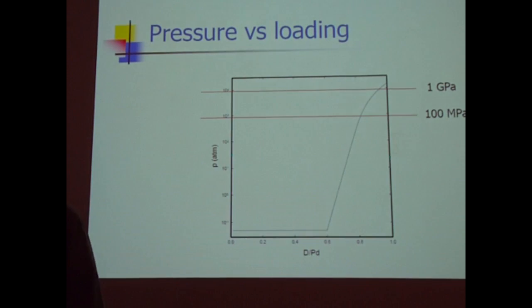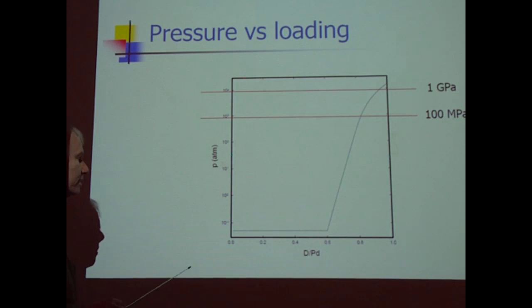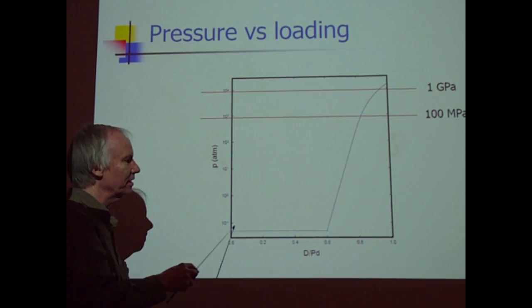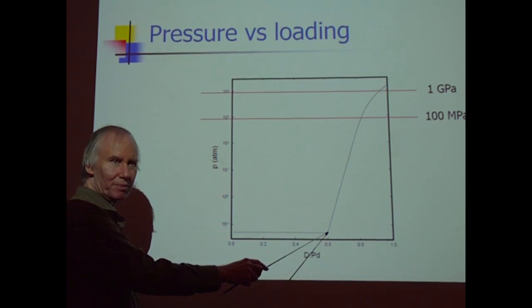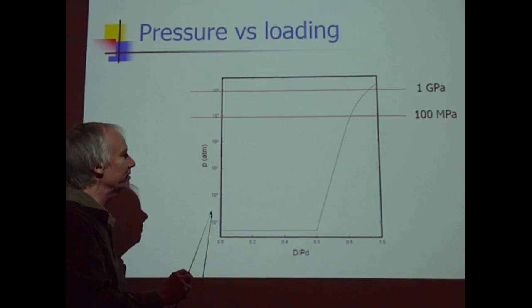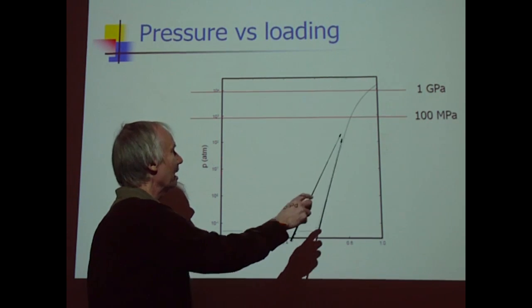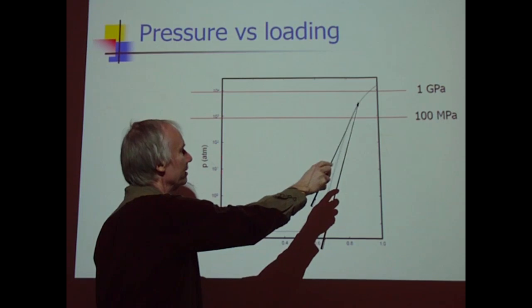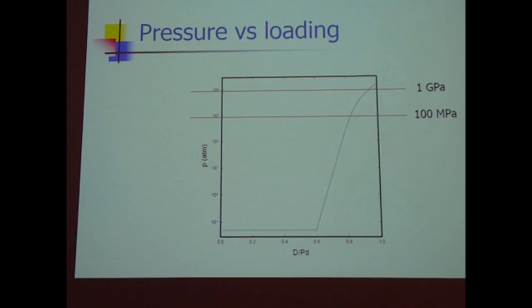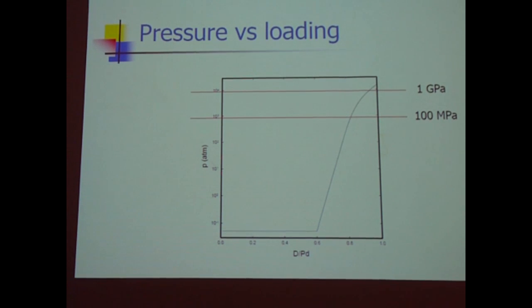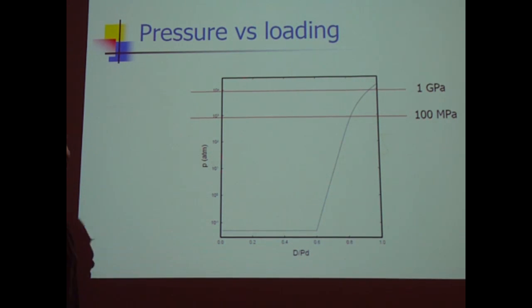Let's think about this as compared with the equivalent palladium deuteride curve. So here's 1/10 of an atmosphere, below 1/10 of an atmosphere. So you can load to the miscibility gap in palladium deuteride at a relatively low number of atmospheres. If you want to get across the miscibility gap in nickel hydride near room temperature, you've got to go to 4000. You're way up here. So to get loading across the miscibility gap in nickel hydride, you have to have electrochemical loading, which is equivalent to being incredibly heroic in palladium hydride, palladium deuteride. You can load it, but it's not easy. So this is what we just argued.